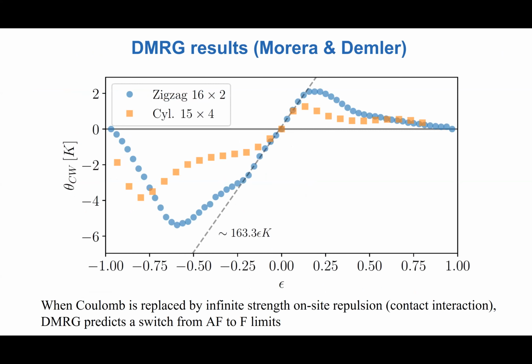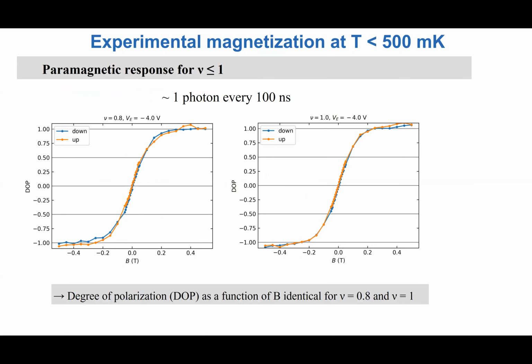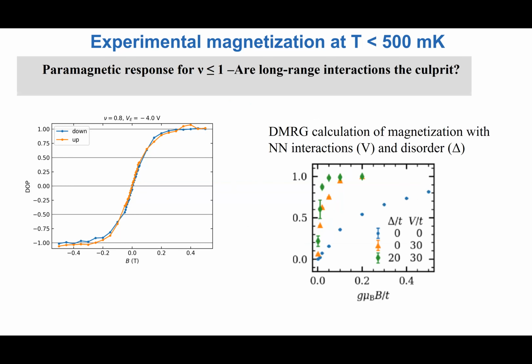These are the results that Ivan did using DMRG with only very strong on-site repulsion. And indeed, it seems to reproduce qualitatively the features. But there was a difference in the details. When we did the measurements at very low temperatures, at very, very low powers, down to picowatts per micron squared, which is like one photon arriving every 100 nanoseconds, so very rare, what we see is that the magnetization measured through attractive polaron resonances as a function of magnetic field is identical for nu equals 0.8 and 1. So basically, the system doesn't seem to want to go antiferromagnetic at all.